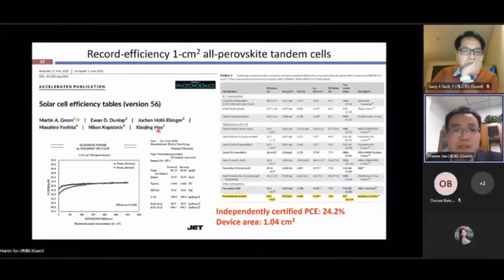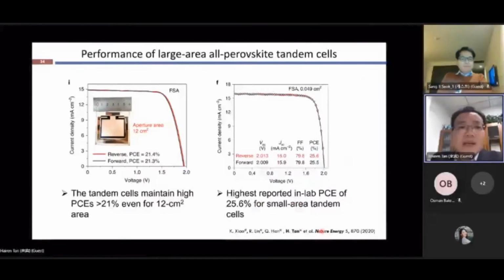We can also see that for the single junction perovskite solar cells with the same device area, the efficiency is 21.6%. So it means there's no reason that the tandem devices cannot be fabricated in larger area compared to the single junction devices. We even tried to make larger area devices, with an active area of 12 square centimeters on a 6 by 6 centimeter substrate, and we can still get efficiency of about 21%. Also, due to the surface passivation in the narrow band gap subcell, we can get a higher VOC than previous work, and we increased the efficiency to 25.6% at that time.